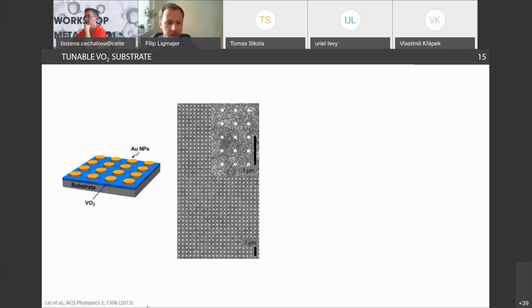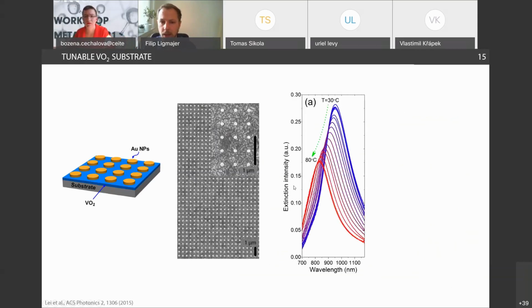This all started in 2015 when I was an Erasmus student in Stefan Meyer's group, and with Daniel Ley we were investigating how actually this tunable substrate, this VO2 thin film under gold nanoparticles, gold nanodiscs, influences the plasmonic resonance of these gold nanoparticles. And we got quite nice results that by tuning the temperature from 30 to 80 degrees across the phase transition, you are able to tune the plasmonic resonance. Here is extinction intensity, which is proportional to the amount of scattering and absorption happening in the gold nanoparticles. How this plasmonic resonance shifts to short wavelengths because the VO2 underneath undergoes the characteristic phase transition.